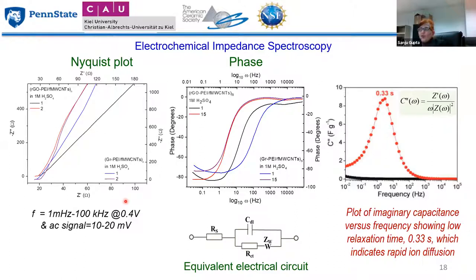And then we also performed electrochemical impedance spectroscopy. So this configuration of the metal electrode and then the graphene and carbon nanotubes, which is your active material, can be modeled with what we call the Randles circuit, or equivalent electrical circuit, which is basically an RC circuit. But then there are other parameters that you can see here. This is the solution resistance. Then you have a double layer capacitor, and then there's a charge transfer resistance. And then there is something called a Warburg impedance. The Warburg impedance is the low frequency response, which is around here, and this is the high frequency response.